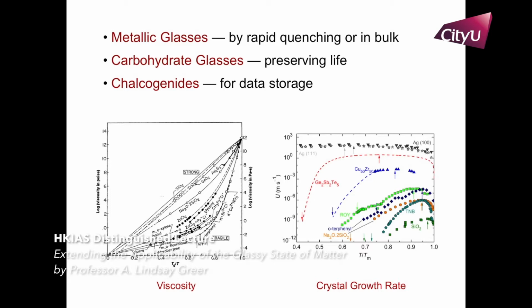whether you're looking at viscosity as a function of temperature or growth rate as a function of temperature. Here is silica on this side. This would be like a pure metal system. You get spectra of behavior which relate the different glasses to each other, which is quite remarkable. You don't tend to get similar correlations pointed out for crystalline materials. And that's our point where we'll leave it. Thank you very much.